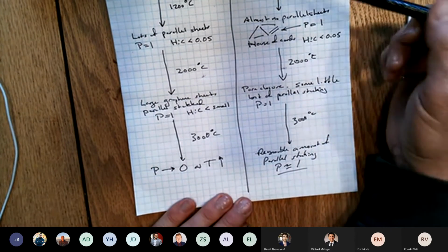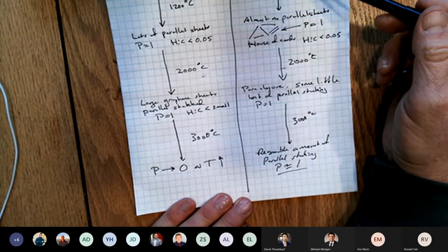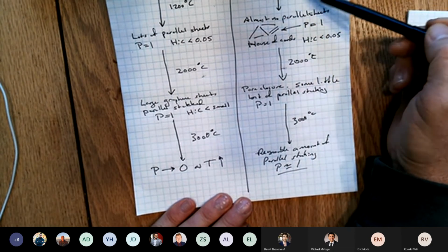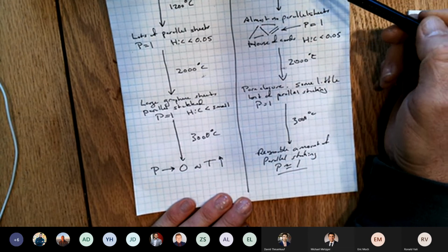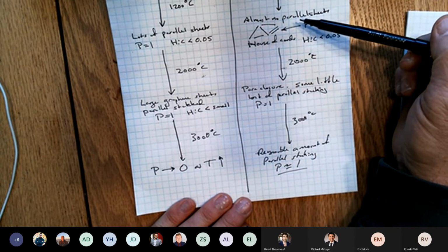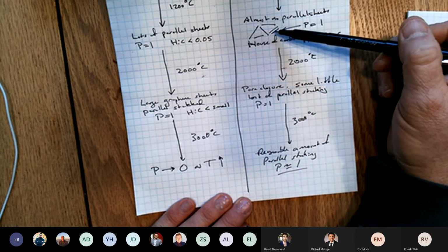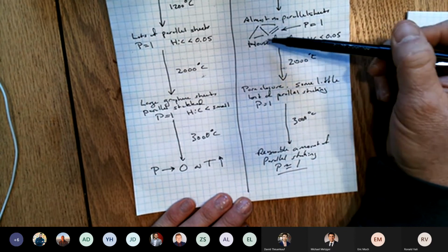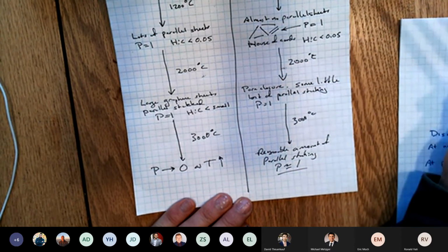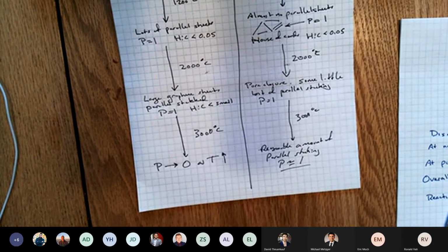And it all comes about way back in the beginning where there was no fluid phase that forms, and you sort of lock the carbon into sp3 bonding at certain places. And then it's just really hard to have all these sheets align and graphitize. So that's kind of a story about how these carbons evolve with temperature.